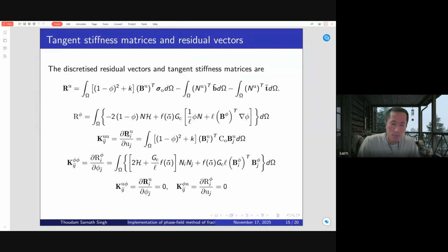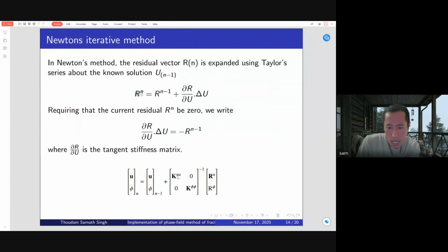And this is the tangent stiffness matrix for solving the displacement, and this is the tangent stiffness matrix for solving the phase field equation. In the earlier slide, I have shown that in this matrix we have K u u and K phi phi. But we have this term 0 and this term also 0. So these two terms are 0 because